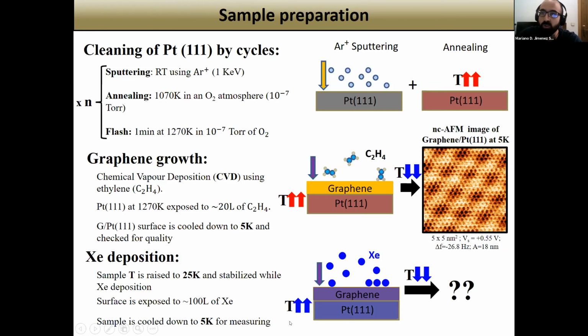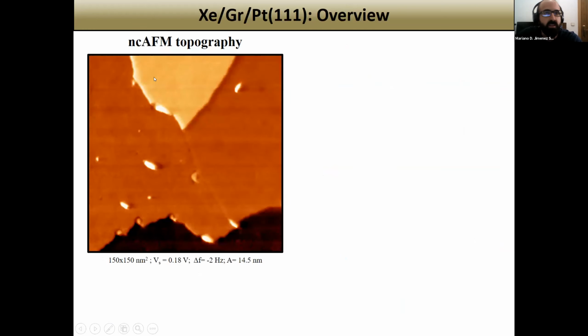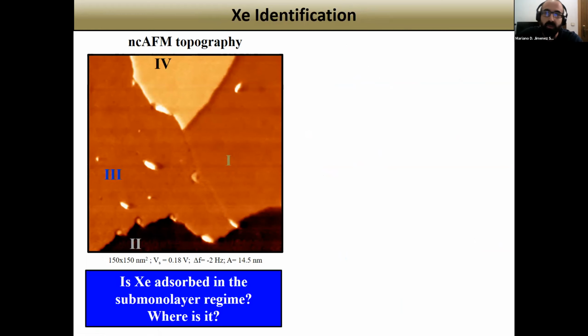Well, and how does the sample look after all this process? Well, this is an ncAFM image of the surface, which shows an overview after the process. This image has been processed in order to highlight the different boundaries, in particular, this one here. Well, what we observe here is that we have 4 different regions. And the first question that comes to mind is, is xenon adsorbed in the submonolayer regime? And if it is, where is it? Well, a first attempt to identify xenon could be, well, maybe this is graphene, those could be 2 different flakes of graphene, and perhaps this is a xenon island.